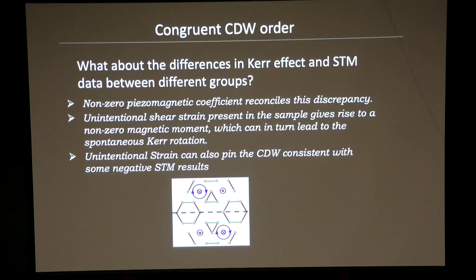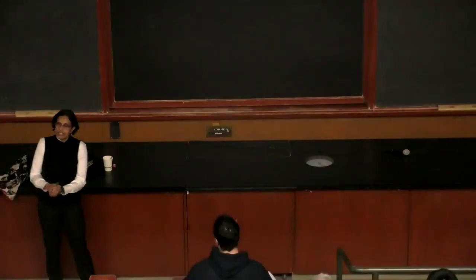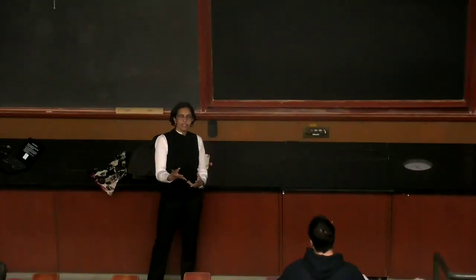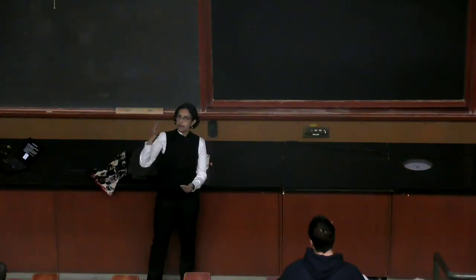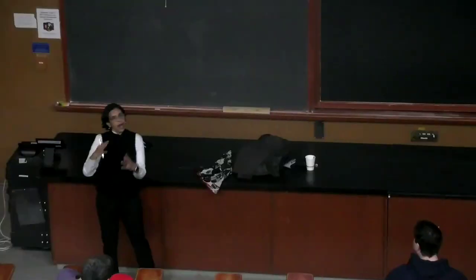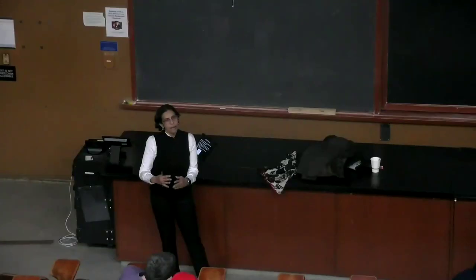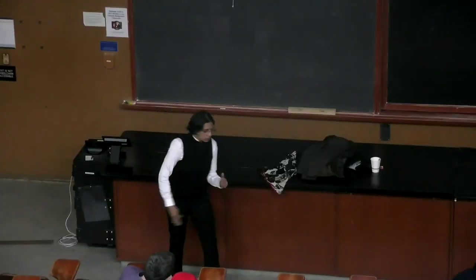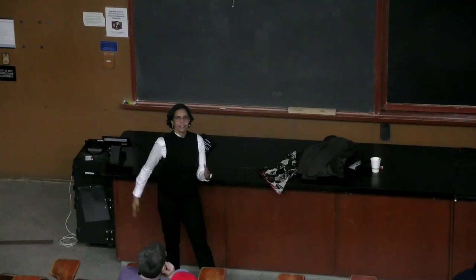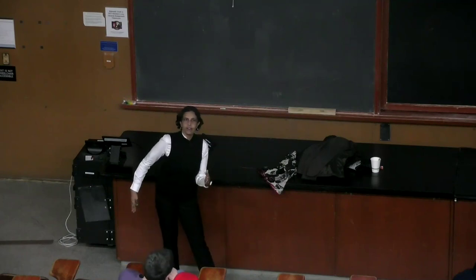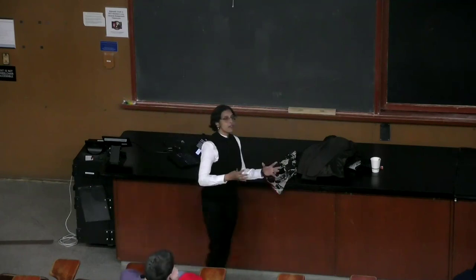So essentially, the material is extremely sensitive to strain. We ourselves have seen this. Remember the magnetic field thing that I was telling you, where the charge density wave intensities actually change with magnetic field? There are areas which are highly strained in the same sample. We can see that because there's usually a line, a dislocation line or something like that running through that area. And if you go to those areas and try to do the magnetic field studies, you see nothing.